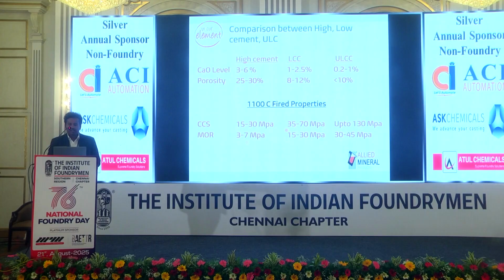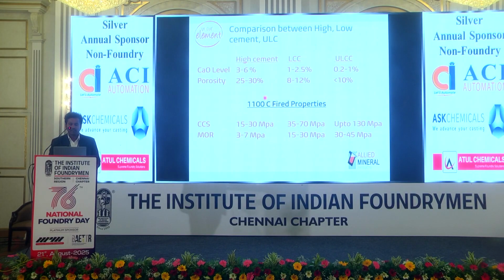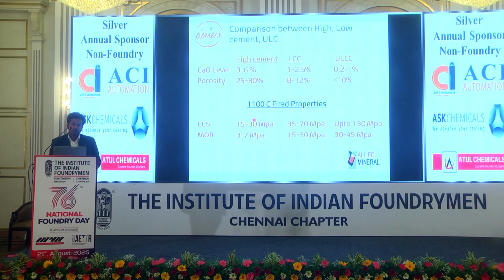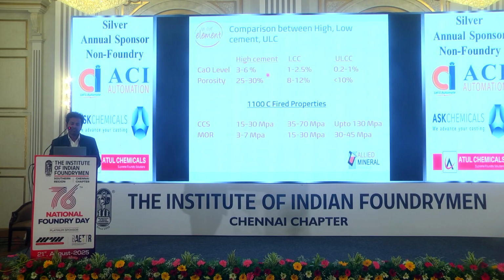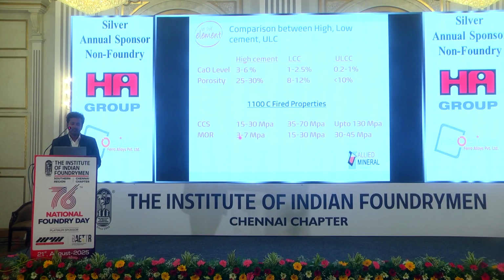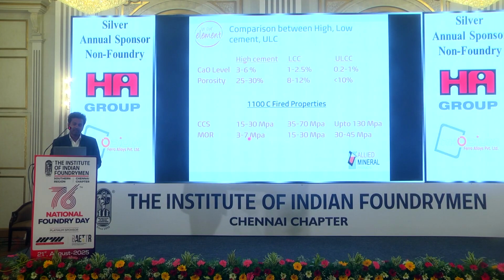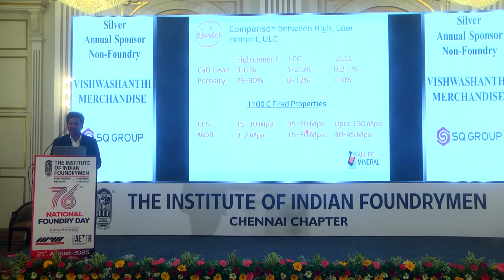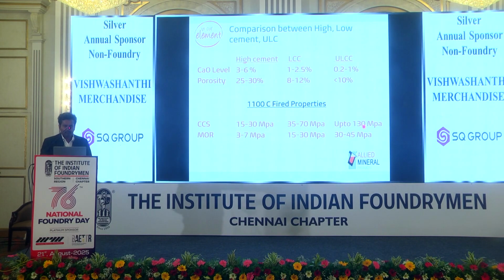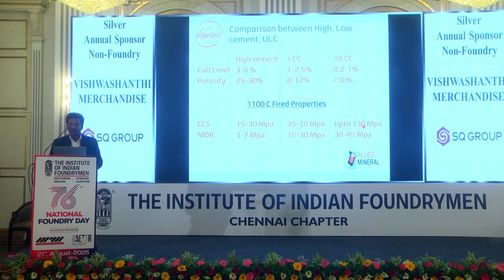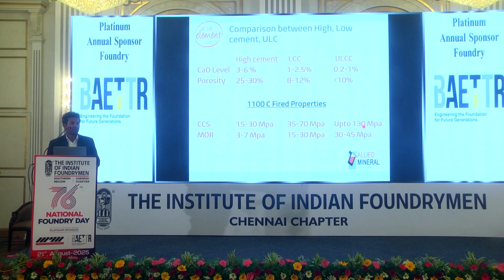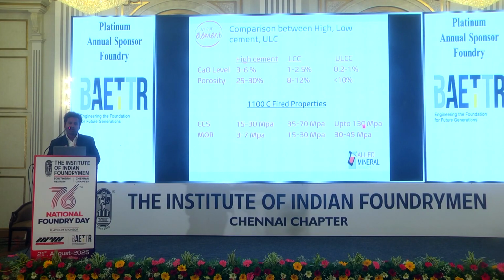So this chart gives a general idea about the cement percentage, porosity percentage and the strength. If you see, high cement has a very high porosity level and very little strength. So 15 to 30 megapascal, and 3 to 7 megapascal modulus of rupture at 1100 degrees Celsius. Low cement has 70 megapascal and ultra low cement can achieve strength of up to 130 megapascal. At the same time, we cannot have ultra low cement for all applications because it contains some special raw materials and special additives, so it may be expensive, but we have to think and decide on the product according to the needs.